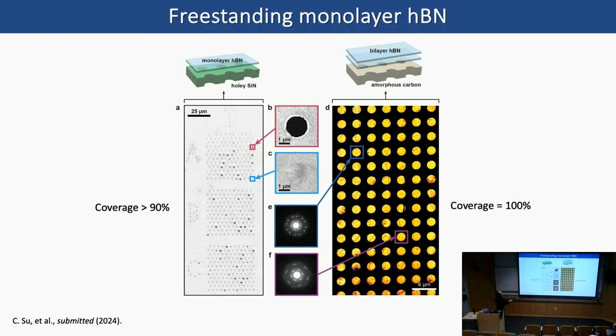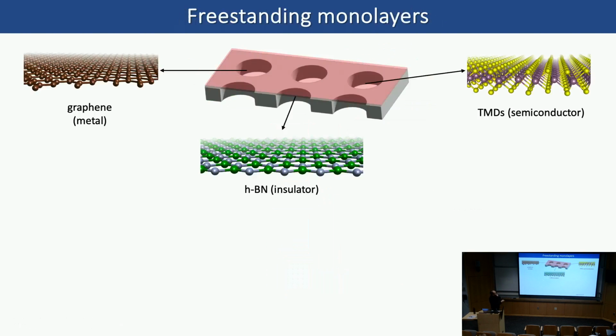And we recently figured out a way to transfer monolayer hBN to the TEM grid so that it makes a freestanding material. The outcome is that for monolayer hBN, we could get a pretty nice coverage. And then we could also repeat the process and create a bilayer hBN where we could get different twisted regions, which is very important for investigating twisted hBN, what the mechanism is, right? So these are something we're pretty excited about.